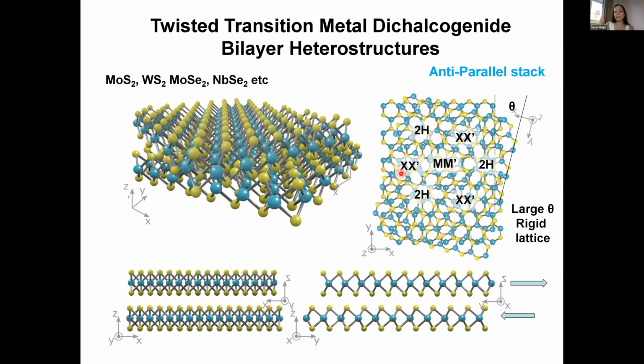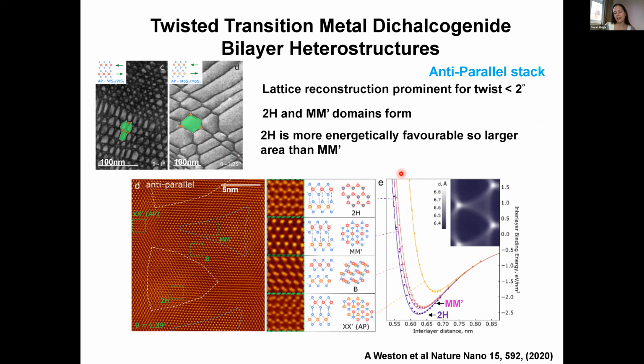And this leads to a completely different domain structure that really hasn't ever been seen before. Because these 2H domains are by far the most stable region, and the metal-metal regions are more stable than a completely incommensurate lattice, but not as stable, we end up with this type of reconstruction here. As you can see, we have these large 2H type domains, which are kind of hexagonal, and they're separated by these small metal-metal triangular domain regions.